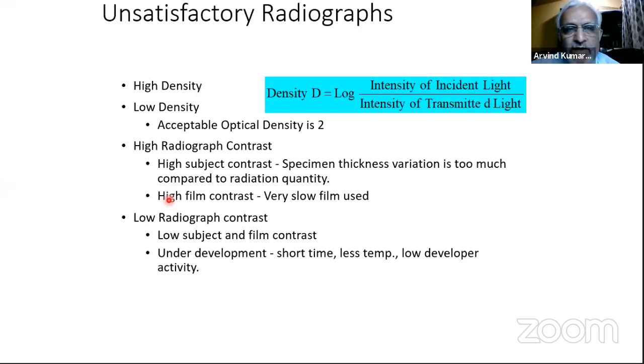Then whether the contrast, density and sensitivity are okay, everything is okay, then you start the interpretation for looking for the defects. So there are two things to be seen before you actually start evaluating a radiograph. One is whether it has any process marks or spurious indications which are masking my defect area of interest. The other is that proper exposure times, density and sensitivity are achieved, as required for that particular technique and the thickness of the job that is being radiographed. Once that is meeting the requirement, then you can evaluate the radiograph as per the code that you're following.